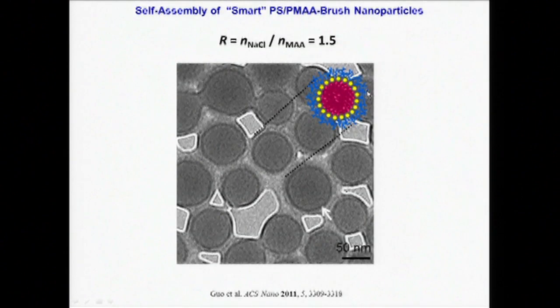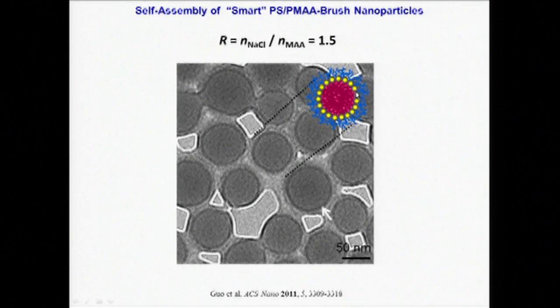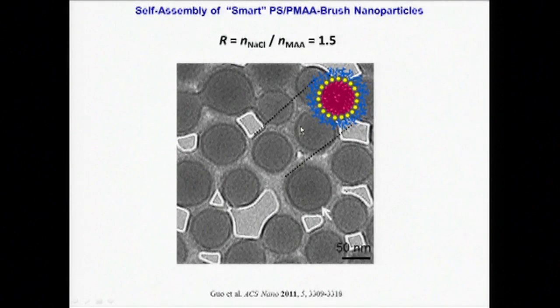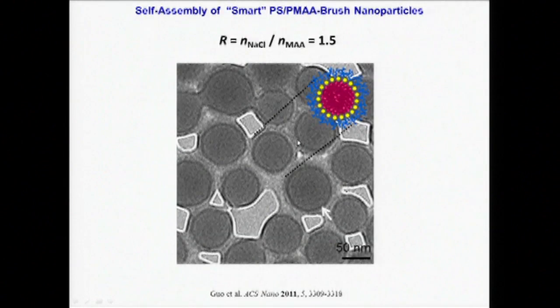Notice that in these structures, all of the charged hydrophilic blocks are on the outside of the micelle core — in other words, solubilized in water — which becomes thermodynamically favorable due to screening of electrostatic repulsion between polymethacrylic acid chains when a controlled amount of salt is added.